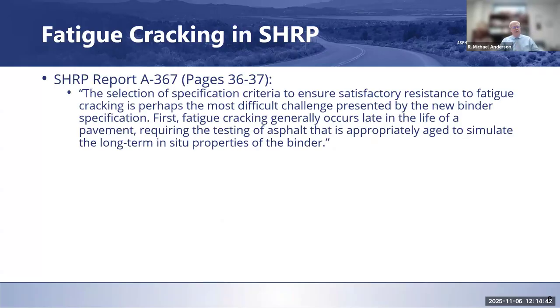So during SHRP, how did they address fatigue cracking? If you go to SHRP report A367, it talks about, and this is a lot of words here, how they selected the specification criteria so that you got satisfactory resistance to fatigue cracking. Basically, within an asphalt binder specification, what you want the asphalt binder to do is to do its part. You don't want it to be the cause of a failure. It's not going to be able to overcome those weak subgrades or whatever have you. It just needs to not be the reason why the failure is occurring.